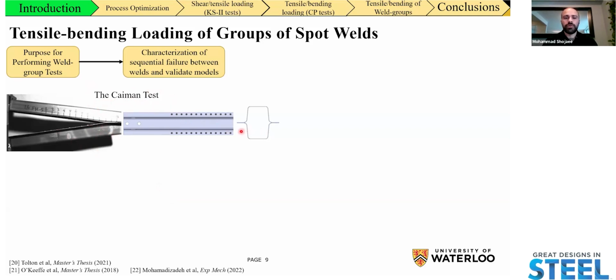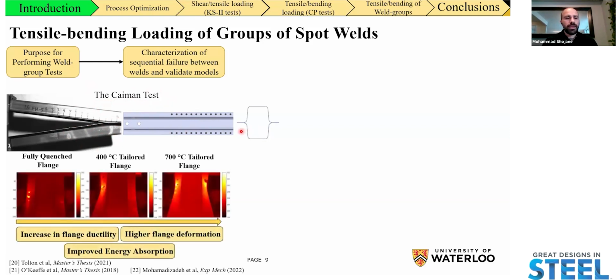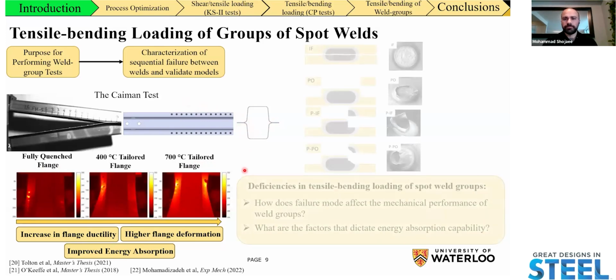It is comprised of two hat channel rails that are welded together on the flanges. And from what we know from the literature is that the mechanical performance of the spot welds that we attained from the Caiman test really depends on ductility of the flanges where the spot welds are located. So in a study in 2021, what we really understood is that if we tailor the properties of the flange by heat treating it, we can improve the mechanical performance of the weld by increasing the ductility of the flanges.